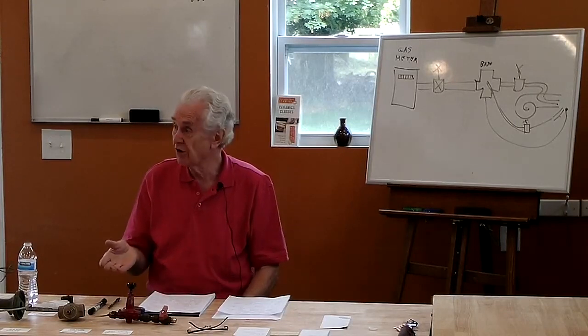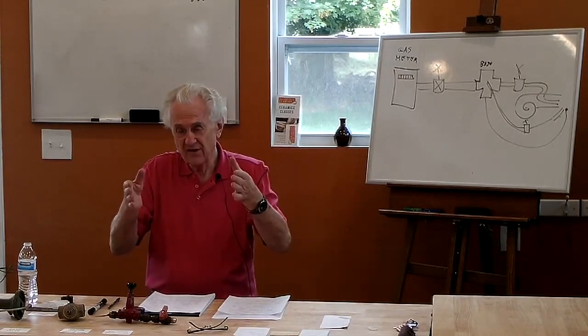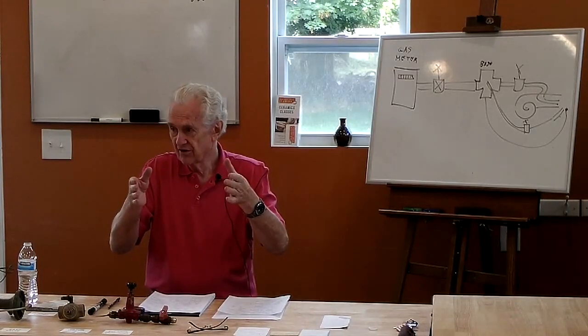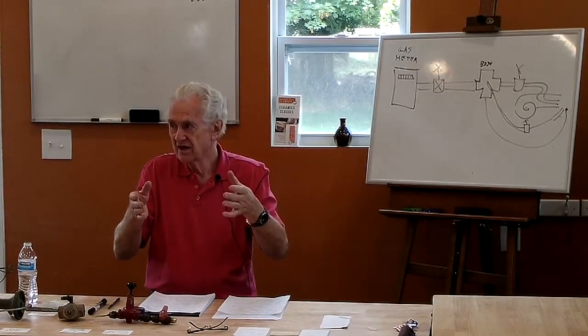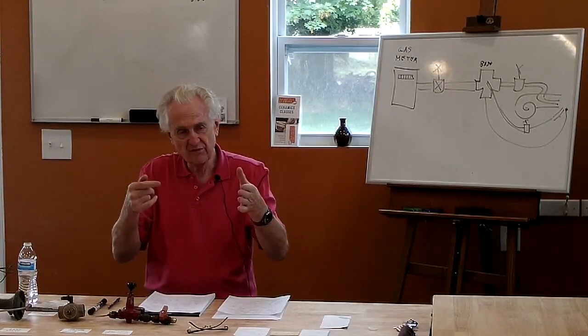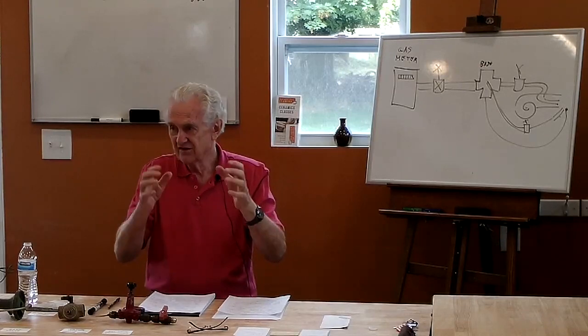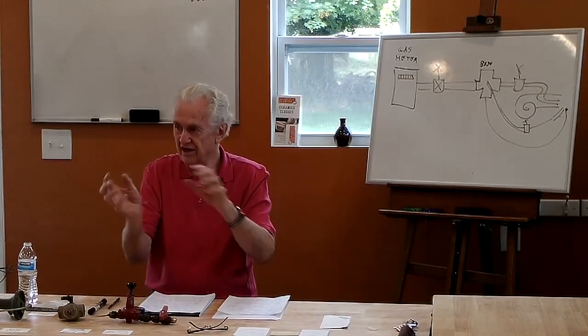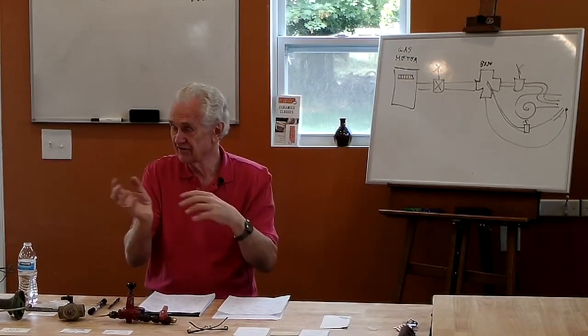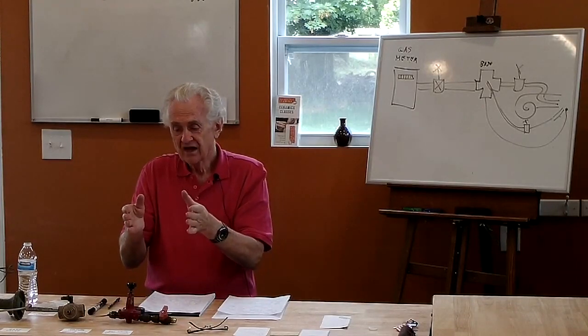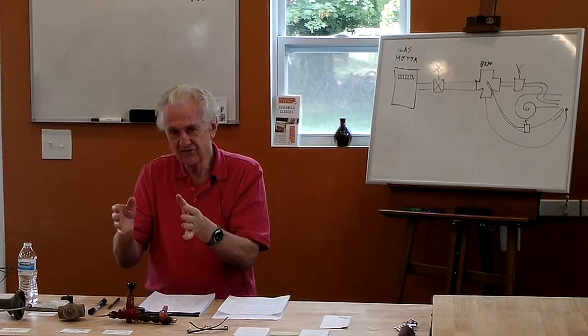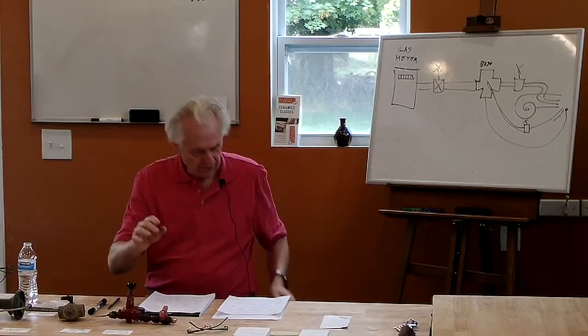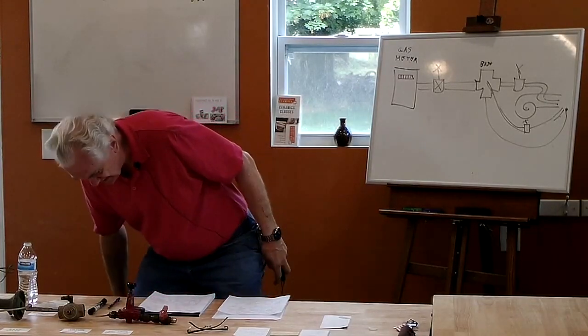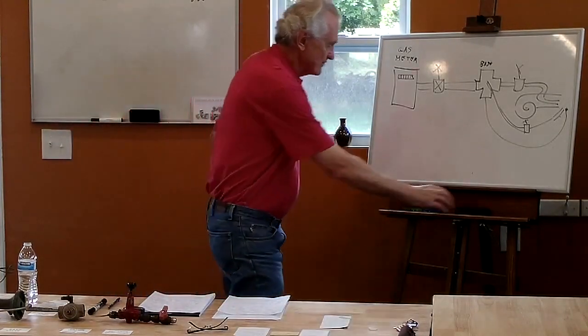One of them is a bag wall, which is a wall that separates where the gases are coming in from the wear chamber. And you might even purposely point the burners at the bag wall, which means the gases are blasting on this wall, and it creates turbulence and tends to mix the gas and the air. Or I can have a separate little space that the burner blasts into, and it gives a chance for the gas and the air to mix before it actually hits the pot.